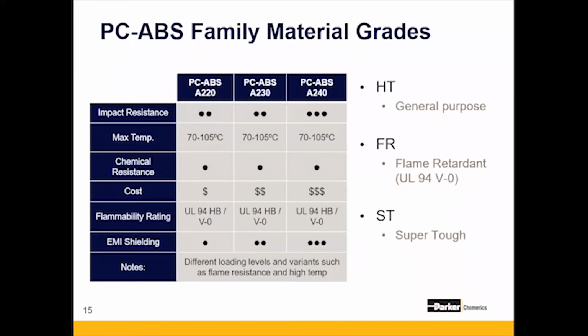And then last but not least, the ST, the super tough. The way it gets to be super tough is we're using more PC in the alloy and less ABS. PC is a highly impact resistant material; your safety goggles are all polycarbonate. Using more PC, you're going to get better impact performance, but you're also going to get better impact performance from being an all fiber material, so that doesn't have any of the granular fillers. All that fiber, it's like a carbon fiber reinforced material. We've had customers that made boxes and dropped them 30 feet on concrete floors, and the boxes survived great. The electronics might have got a little messed up on the inside, but the boxes were great.